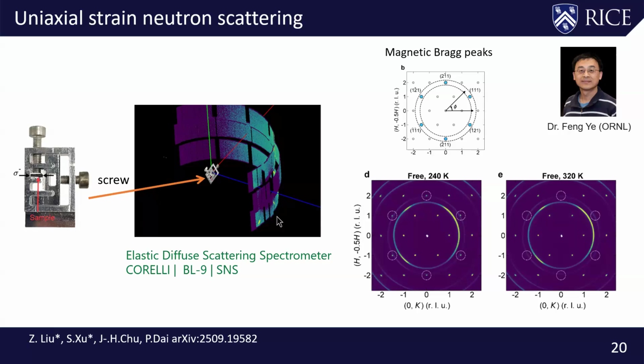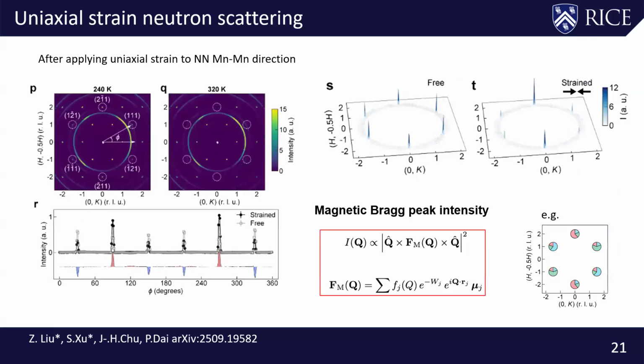And this is actually done at Oak Ridge on an instrument called the Corelli. You don't have to know the details, but neutron scattering looks at the magnetic moment that is perpendicular to the momentum transfer Q, and also perpendicular to the neutron spin direction. Within these 2 models you should expect to see 6 magnetic Bragg peaks at these positions.